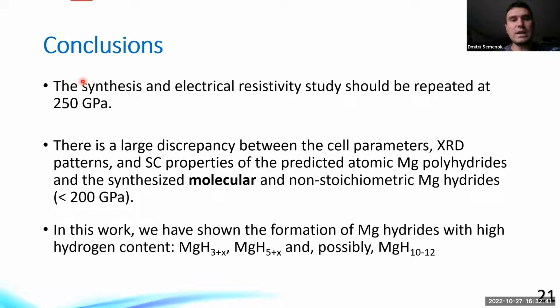In this work, we have shown the formation of really perspective and interesting compounds. Magnesium reacts with hydrogen and forms magnesium H3 plus x, magnesium H5 plus x, and possibly higher magnesium hydrides, such as magnesium H10, 12. We need to do additional experiments. Maybe we will be able to do it in 2023 at higher pressure, and we will try to confirm the formation of these compounds and maybe even get new information about these higher magnesium polyhydrides.